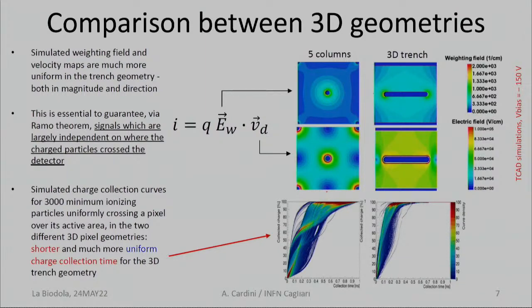depending on the position of the impact of a particle in your detector, does not change very much. While this is not true in a cylindrical-like design, as you can see here. You see the charge here, it's much slower, the charge collection time, and it's much spread. Those plots are obtained from uniform illumination of your active area. So it's the 1/r dependence on the field that kills you, compared to a constant field.